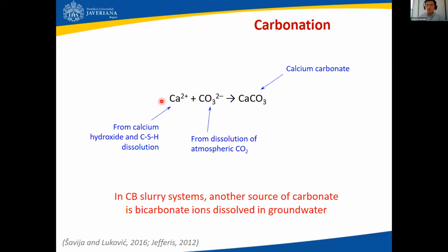A second reaction I want to look at is carbonation. When we have the abundance of calcium from the dissolution of calcium hydroxide and CSH, which, like I say, takes place during cement hydration, when this calcium combines with atmospheric CO2, we know this reaction and it delivers calcium carbonate, the mineral calcium carbonate. So this is well known in the cement chemistry literature. And the interesting thing is that in CB slurry systems, or even in slag-CB slurry systems, which are being constructed at a certain depth, say 15 meters below ground surface, there is probably another source of carbonate, which is bicarbonate ions dissolved in groundwater. So these processes are, in a way, plausible in a slag-CB cutoff.